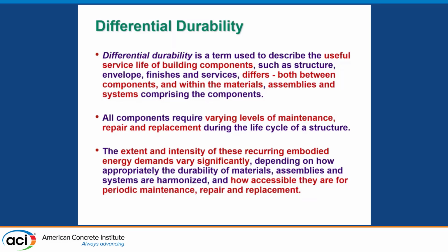And so when you have differential levels of durability, you have varying levels of maintenance, repair, and replacement. And this is what you have to keep in mind: even though you might have built a concrete structure, if you didn't use the proper mortar, or you didn't use a proper type of finishing, or you didn't seal it correctly, you could have many, many areas where you're just racking up CO2. And so it's the extent and the intensity of these kinds of items when we're doing maintenance that we have to keep in mind for the overall amount of embodied energy in a building.